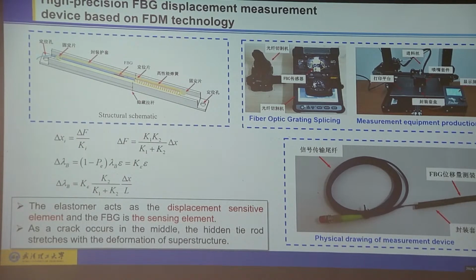This small device is the physical device, like this one. In this device, we have a spring, and this is the fiber Bragg grating sensor, to be installed in the field. If there is some relative deformation, strain will happen here. If you measure the strain, you can understand the deformation between these two points. You can also use this spring to adjust the measurement range. This is the formula which we developed to measure the deformation. This is the deformation between these two points, and this is the relative wavelength shift of the fiber optic sensor. Through this formula, we can measure the deformation through the shift of wavelengths.